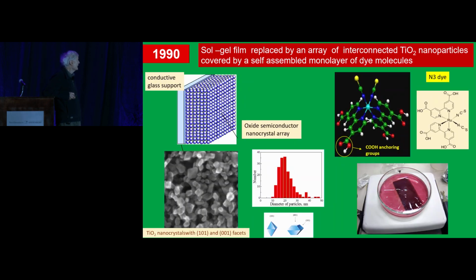The next generation was a real nanocrystal system now, where we used nanoparticles of TiO2 that we arranged in an array of, say, about 5 micron thickness. That enhanced the surface area of this film by several thousand times. So with a monolayer of dye, we were now able to capture the incoming light very efficiently.